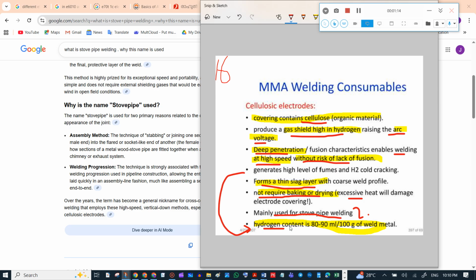The hydrogen content is 80 to 90 ml per 100 gram of weld metal. One disadvantage is it generates a high level of fumes and is susceptible to cold cracking. Hydrogen cold cracking can be observed, so it's a negative point. Now we'll listen to what stovepipe welding is.